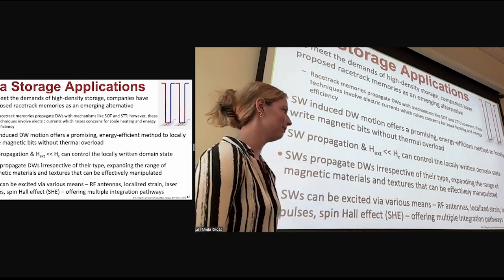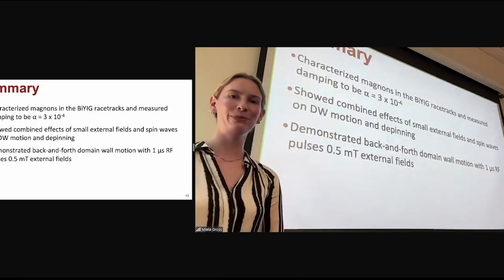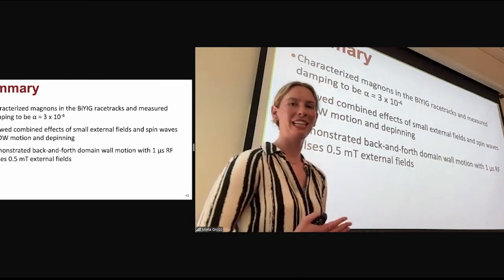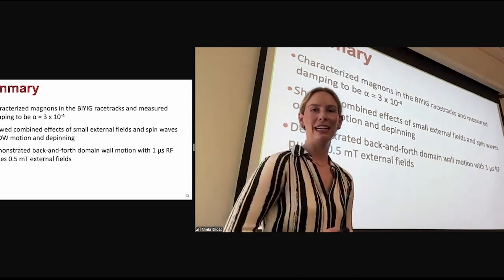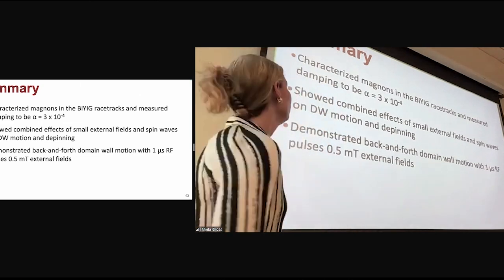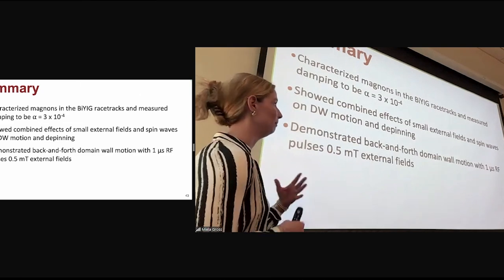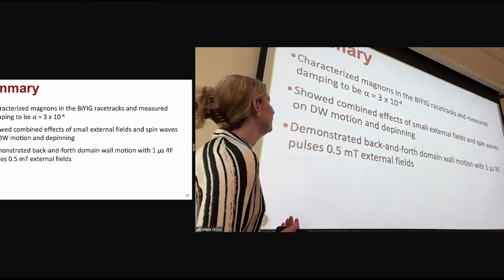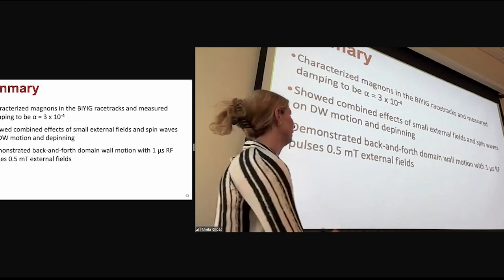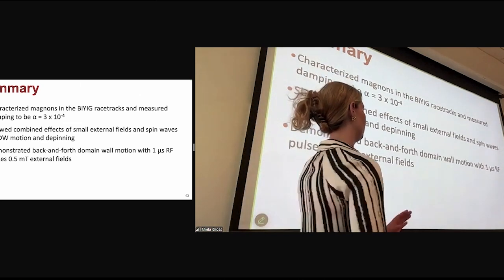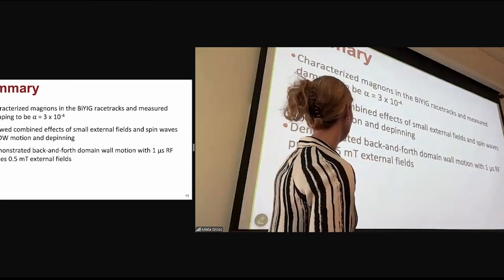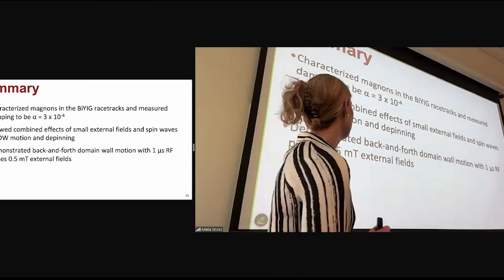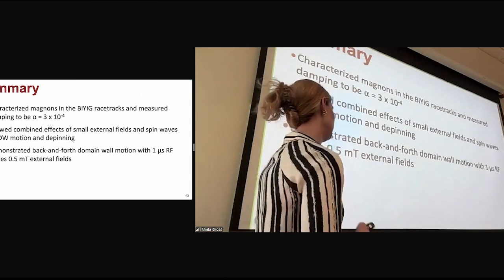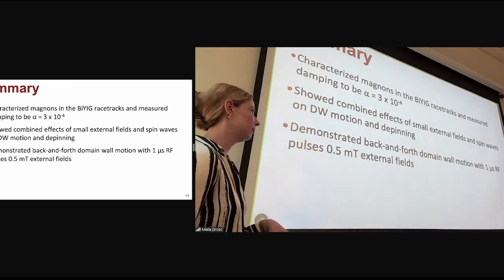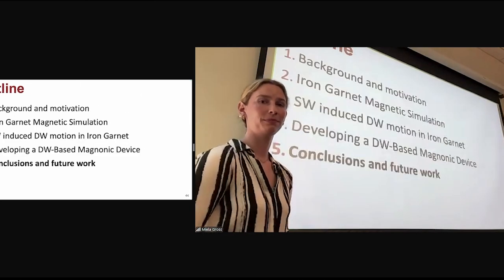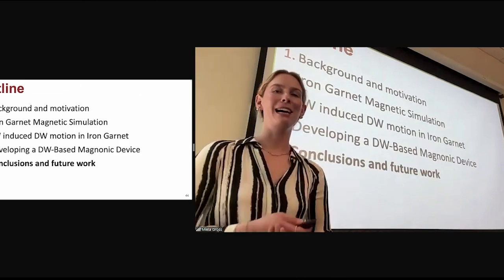So, in summary, I have continued to progress my work with characterizing magnons in the bismuth-YIG racetrack, measuring damping to be 3 times 10 to the -4, which is very low. We showed the combined effects of small external fields and spin waves on domain wall motion and depinning. And then we demonstrated back and forth domain wall motion with just these tiny external fields and microsecond RF pulses. Finally, I get to wrap things up.